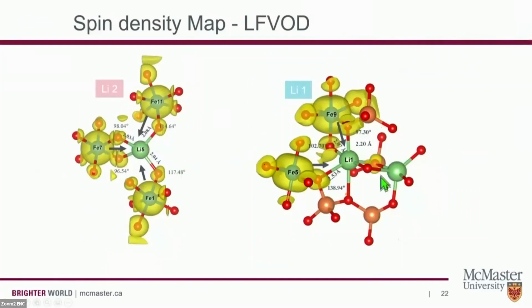This is one example of all the rest of the lithiums which have 2 iron nearest neighbors within the 2.5 angstrom radius. And the lithium-2, that's the new species with a 3rd iron occupying the local coordination environment. So that's a very satisfying understanding of that crystal structure and how the synthesis is playing into what the NMR observables give us. We think this is a really important message that what you get out of one single crystal structure doesn't represent the bulk of the sample. And we heard some ideas around that yesterday as well.